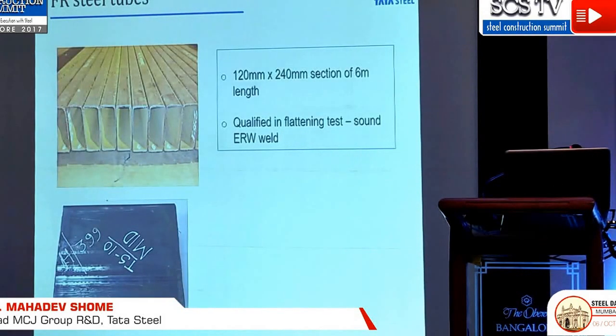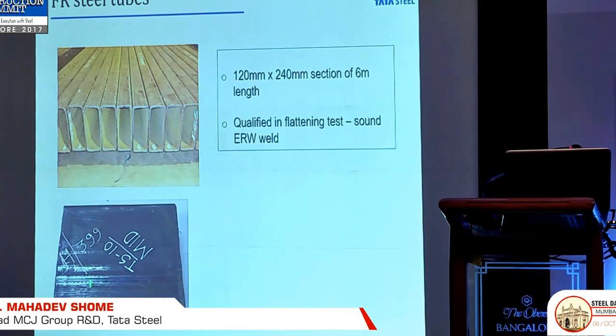And finally, we produced commercially, not only in the lab, more than 1,000 tons of this material, and it has been supplied on a trial basis to various customers. This is just one of the rectangular sections that you see. We could have different sections, round and rectangular. The welds are normally ERW processes, electric resistance welded tubes, and we did quite a good amount of quality assurance exercise to ensure that the welds were sound and the fire resistance could withstand the sort of structural requirements in the marketplace.